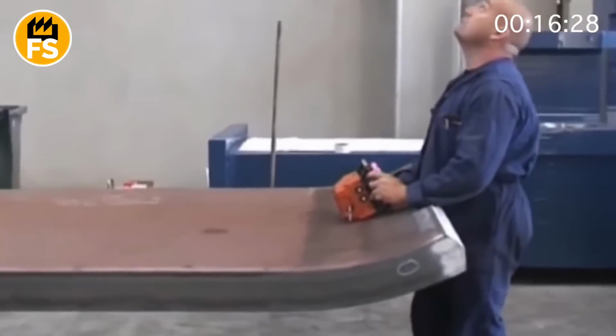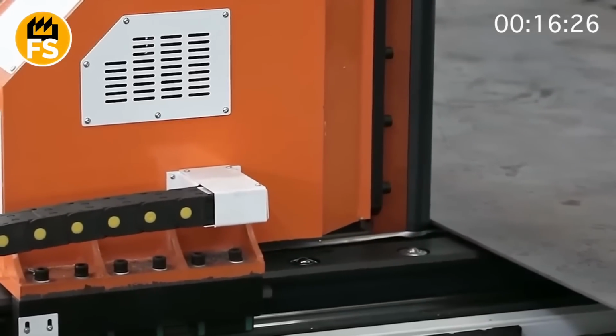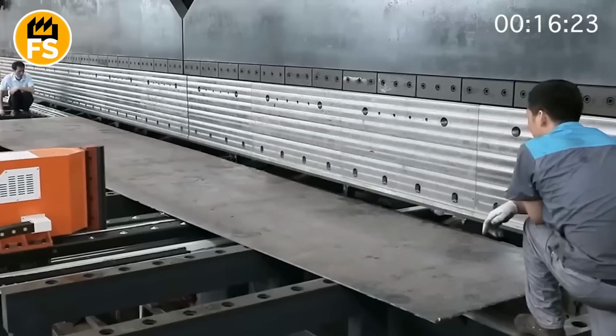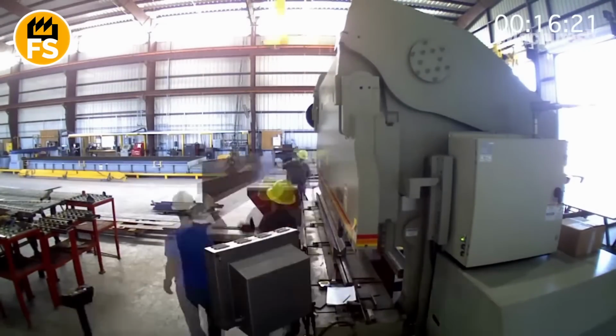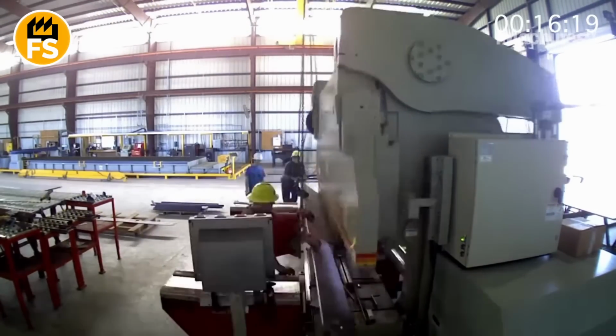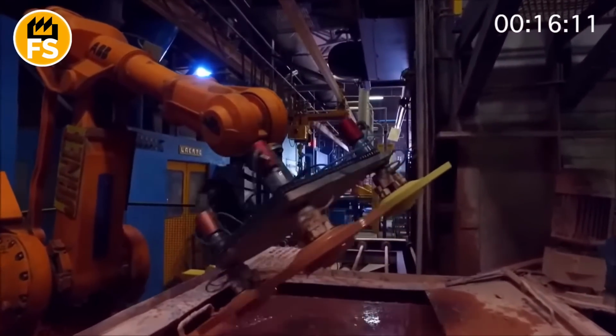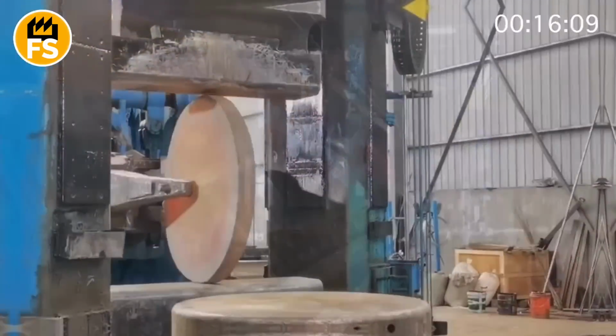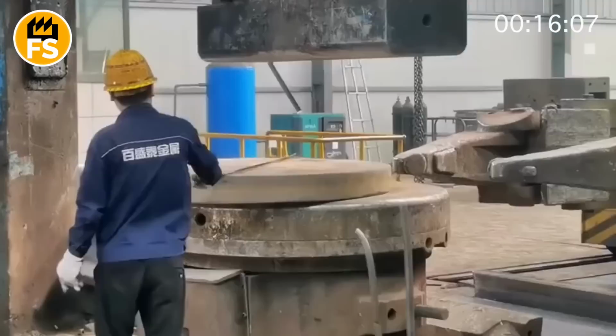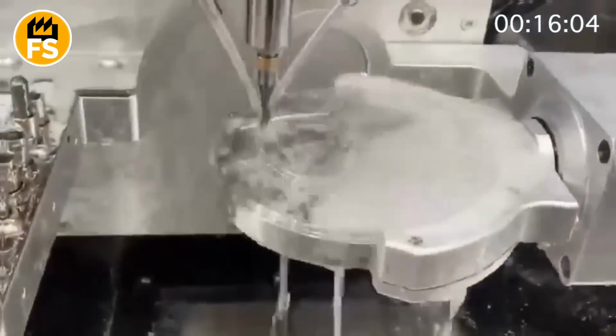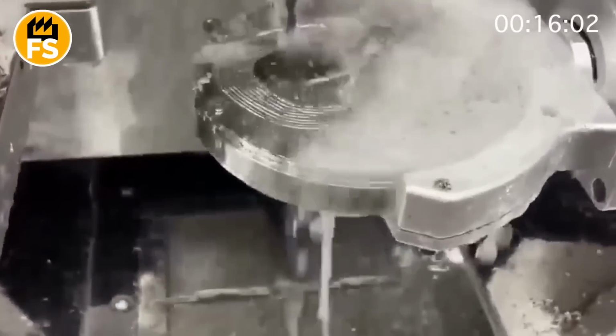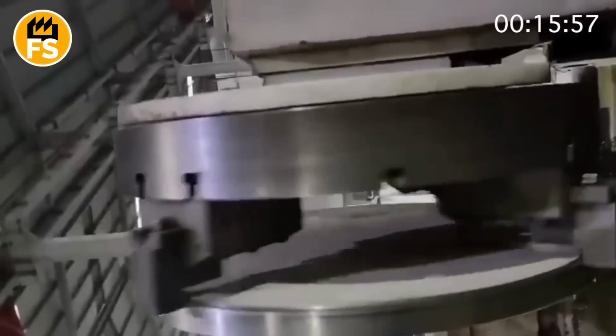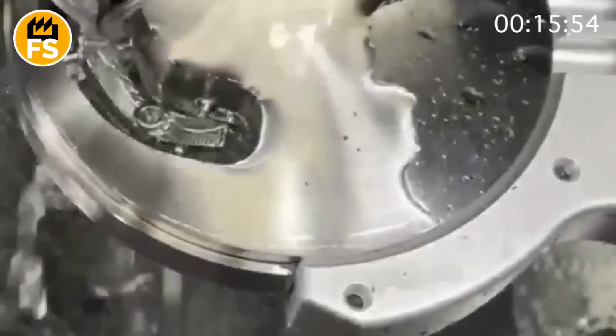Such precision isn't for beauty's sake, it's critical. Because even the slightest error on one flange can cause the spool to lead the cable off-center during rotation. And that's a risk of misalignment, jamming, and failure during installation. The discs for the flanges are cut in pairs, identical rings 20 to 33 feet in diameter, with holes for connecting bolts. Technical slots and markings for future reinforcing elements are made on the surface right away. After cutting, they are processed by grinding machines. Burrs are removed, and they are prepared for welding.